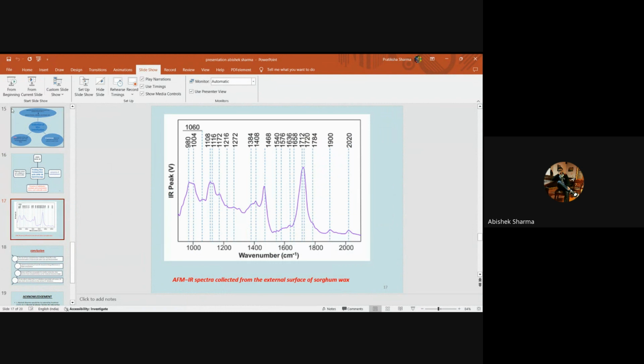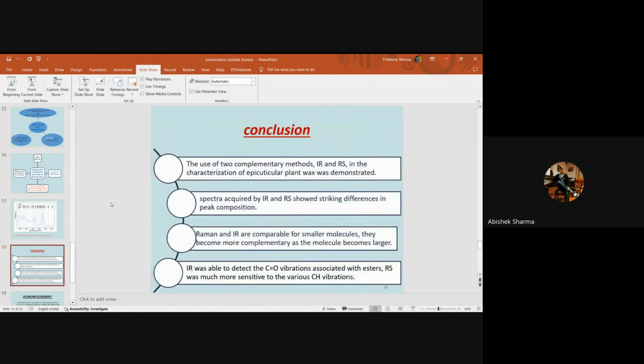So they found the carbonyl vibration in a narrow peak, which suggested the presence of functional groups such as aldehyde, aromatic, unsaturated esters, and carboxylic groups. So we can see that AFM-IR can not only be used for detection and identification of esters in wax, but also for the evaluation of their distribution across the polymer surface. Okay, so my topic is short. So what we have discussed in this experiment is that we used IR and RS, and we saw the complementarity of these techniques to characterize the epicuticular plant wax.